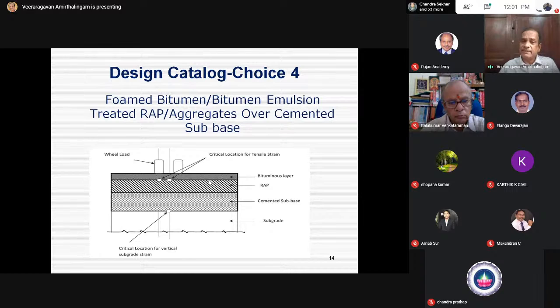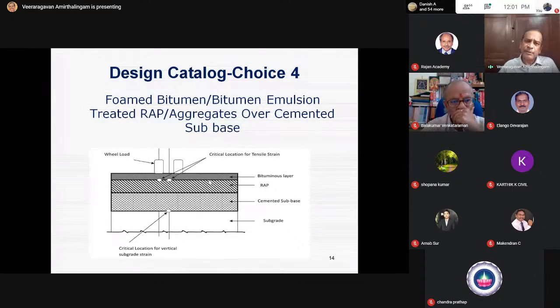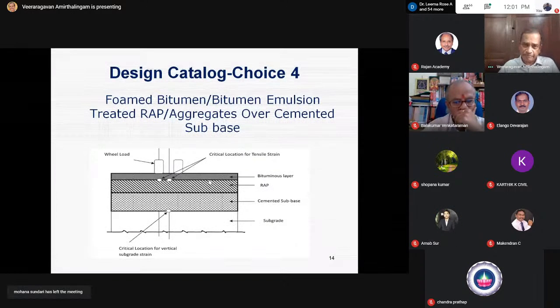In such cases, when aggregates are not available, you can mill the entire material, mill the whole bituminous layer. For example, if you look at Anna Salai, the thickness of bituminous layer in Anna Salai will be more than 30 to 40 centimeters. There is no meaning in providing a thicker overlay above that. I have to resort to recycling. So that's called reclaimed asphalt pavement material, called RAP.